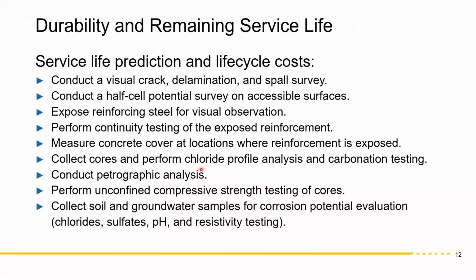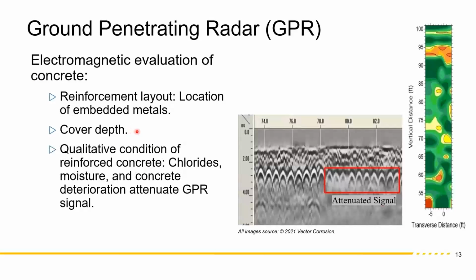So again, the process is you go out in the field, you first do a visual test, say in the column, if you have a concrete column, you look at the visual cracks or do delamination sounding or impact echo testing. Then you look at the corrosion or corrosivity of the element by doing half cell potential or GPR or even a resistivity test. And then once you figure out those areas, you want to core into it and get the chloride profile, and then you want to do repair and get the chloride out so that it makes that component suitable for reuse. So these are the steps taken in corrosion testing.